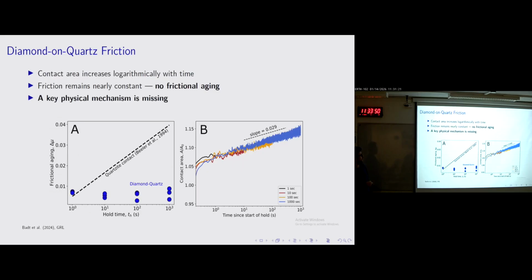Okay, so what we find out is that when we do these scratches with diamond on quartz, the frictional aging delta mu does not really change with hold time. Hold time does not seem to be doing anything, and we definitely don't see the linear increase in frictional aging with hold time from previous experiments. This is diamond on quartz from the nano indenter. This is quartz on quartz from centimeter scale experiments from Badt et al.